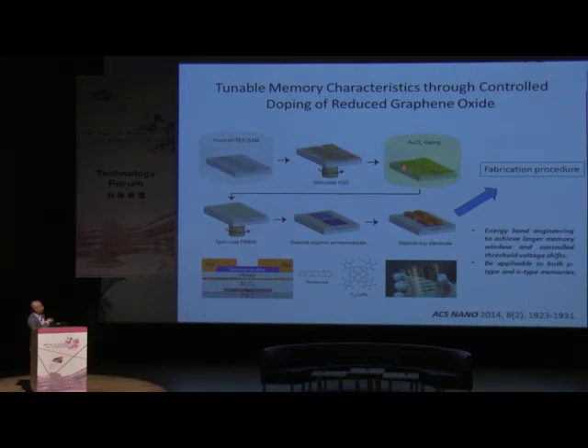First, we put the gold chloride, and because of the negative Gibbs free energy, they have a kind of redox reaction where the charges stick to the surface and release the chloride ions. And at the end, we put the semiconductor on the top and the electrodes. So at the end, the array of memory looks like a piece of plastic. It works in both N-type and P-type mode, meaning both trapping electrons and holes. And you can see the memory window can go up to 2.4 volts, which is much higher than the previous devices.